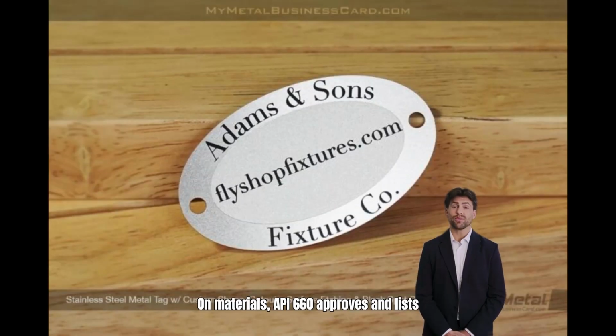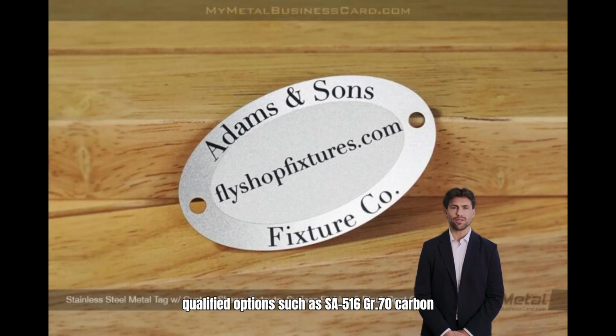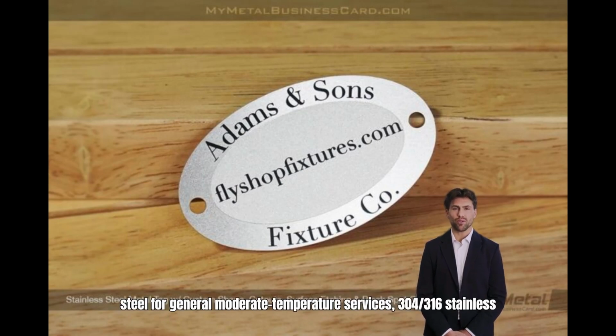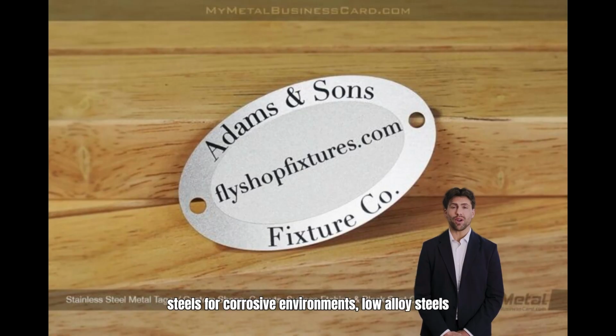On materials, API 660 approves and lists qualified options such as SA-516 Grade 70 carbon steel for general moderate temperature services, 304/316 stainless steels for corrosive environments, low alloy steels like 1.25 Cr-0.5 Mo for high temperatures, duplex stainless for chloride pitting resistance, and Admiralty brass specifically for non-chloride cooling water duties.